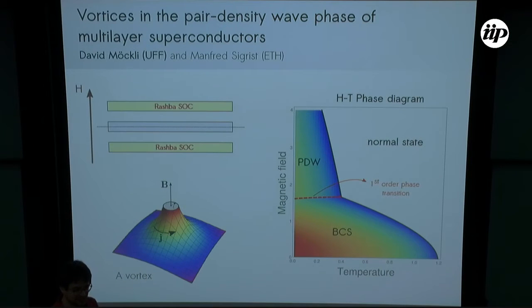At low magnetic field, you just see what you would expect from a Pauli limited system. But at high magnetic fields, you see a new superconducting phase, which is robust against an external magnetic field, which is a pair density wave. It is a parity mixed superconducting phase, for instance S plus P, and it is separated by a first order phase transition. So I want to know what happens if you consider orbital limiting on top of that. Something very interesting happens to the vortex core sizes, which I will show you in more detail at poster number 3. Thank you.